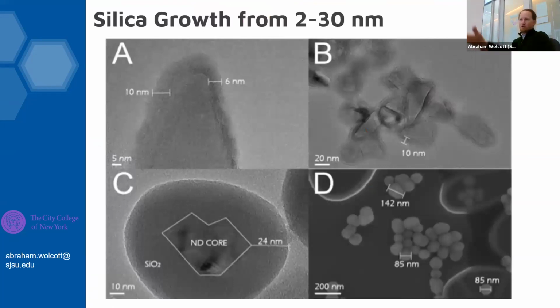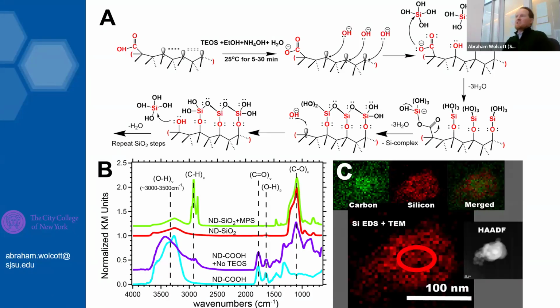So when we do our chemistry, we end up with this level of control. If we wish to stop the silica chemistry, we just finish it after a certain time, and then we go through the purification process. We can get a range somewhere between 2 nanometers and 30 nanometers. What you'll notice is the thicker the shell, the more circular the particles become. This has repercussions in endo- and exocytosis that Peter Sigler and others found out many years ago. So this is a key aspect that I want everybody to pay attention to right here.